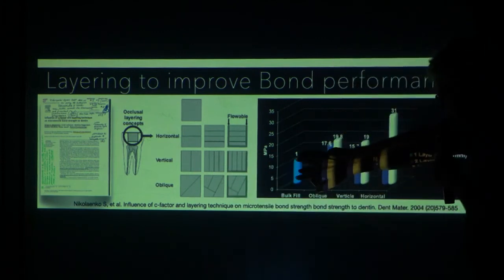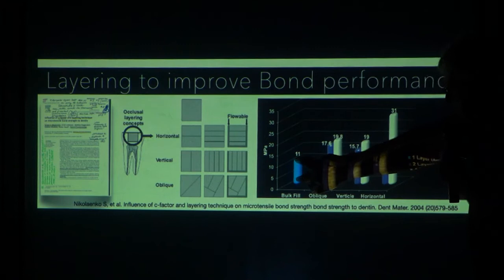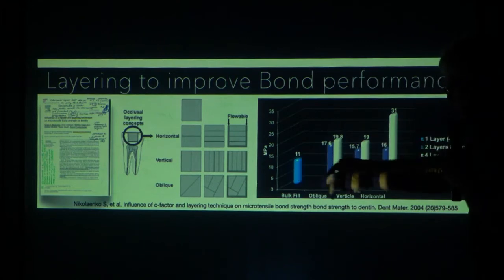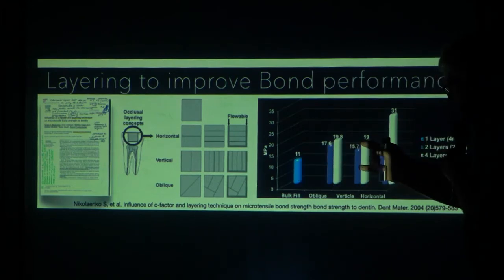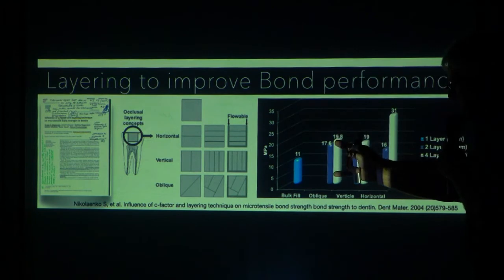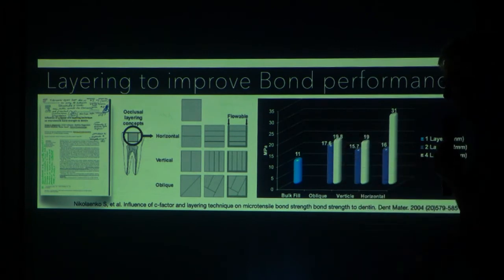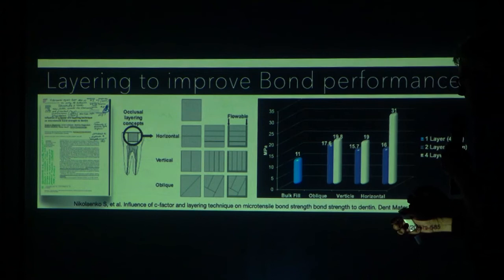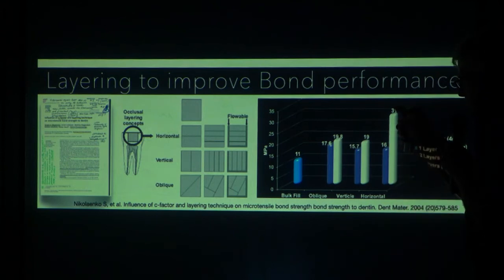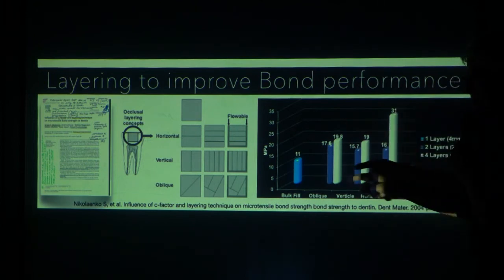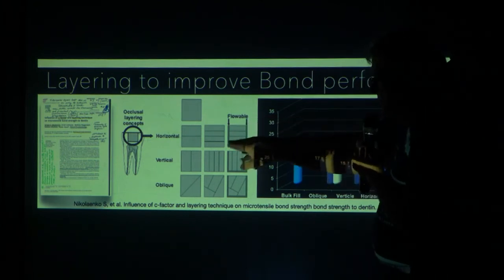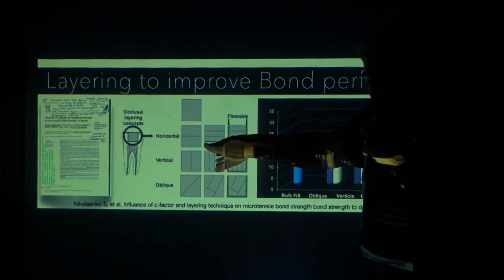And they came out, bulk fill, got 11 megapascal bond strength in the pulpal floor. You can get up to 15, 16, even 19 with the vertical or the oblique. But the only way you can double this bond strength or triple the bond strength from the bulk is to do 4 horizontal increments.